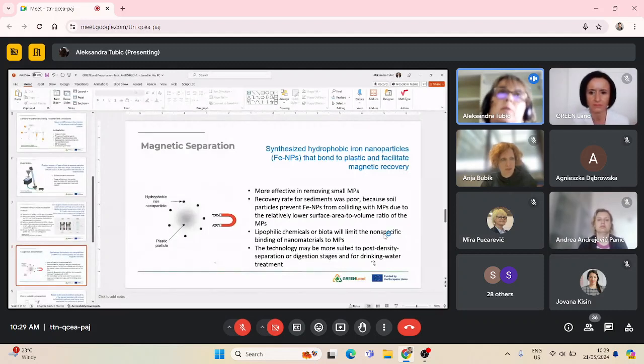Magnetic separation is a new technique, at the very beginning of investigation. Usually synthesized hydrophobic iron nanoparticles are used to bond to the plastic and facilitate magnetic recovery. It is more effective in removing small microplastics. Recovery rate for sediments is poor because soil particles prevent nanoparticles from binding with microplastics, due to the relatively low surface area to volume ratio. Lipophilic chemicals or biota will limit the use of these methods, and the technology may be more suitable for, let's say, post-density separation or digestion stages and for drinking water treatment. But we could also find some information in the literature using this method for soils.